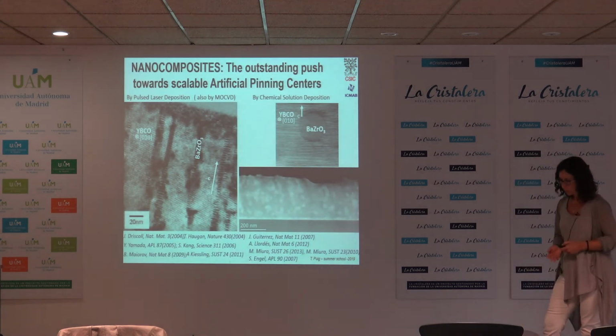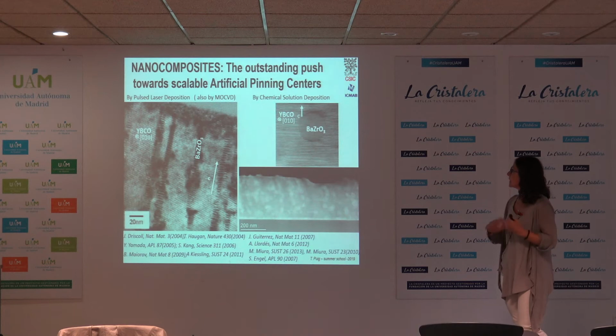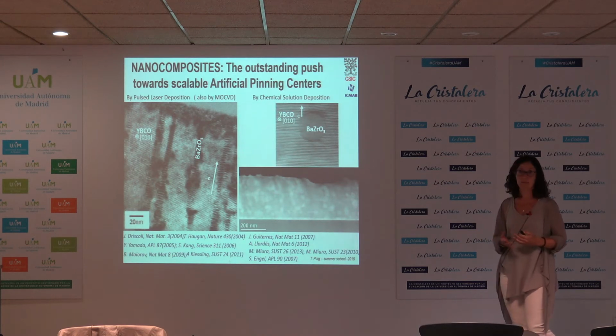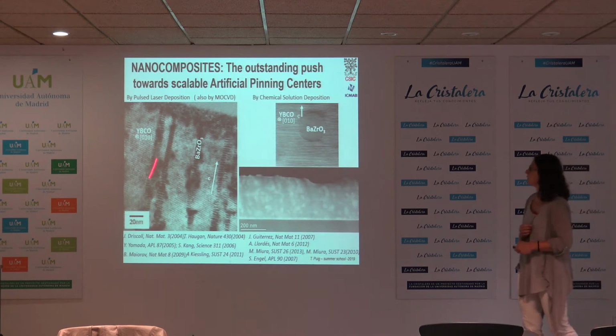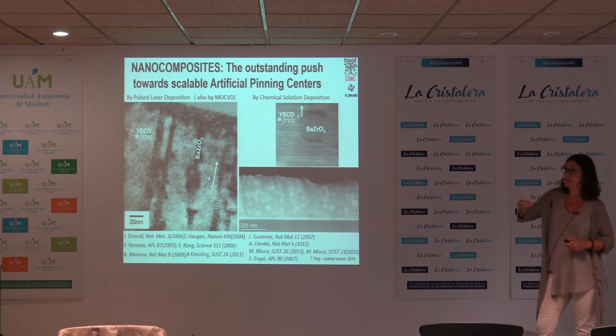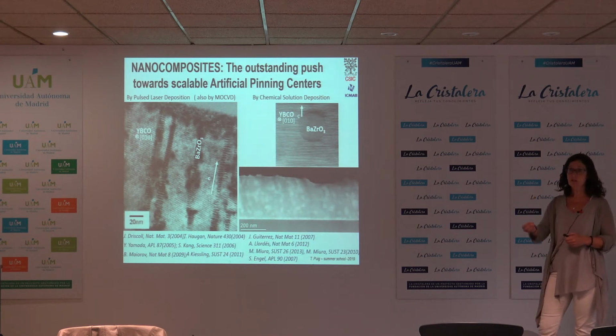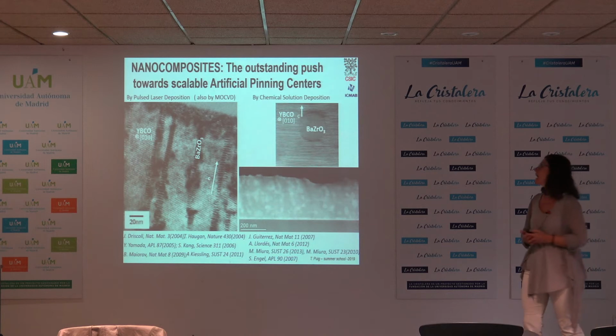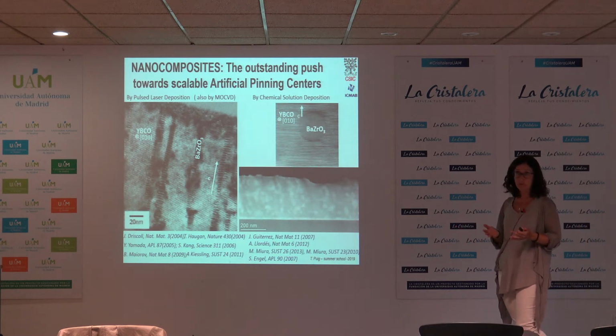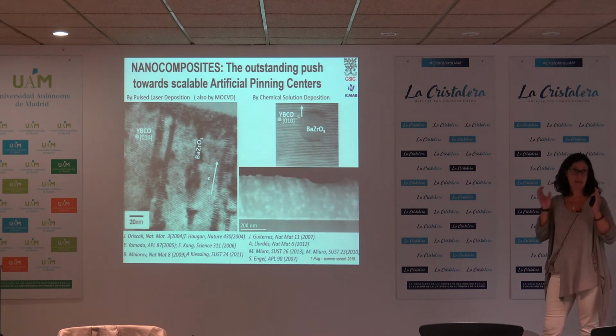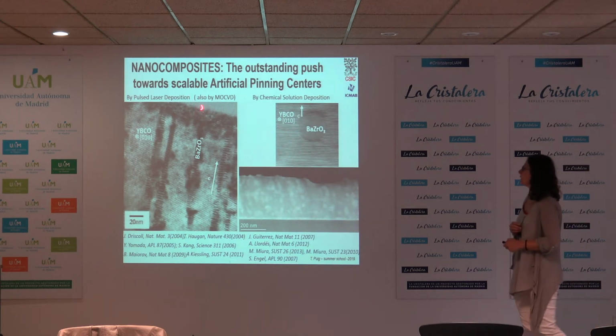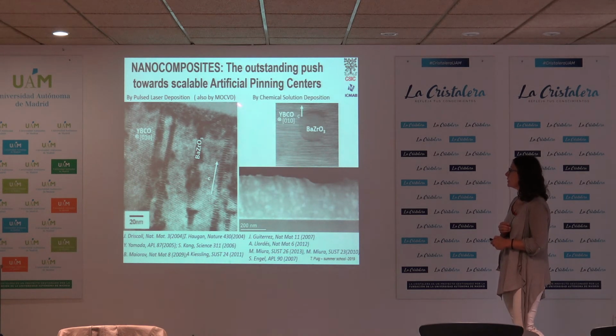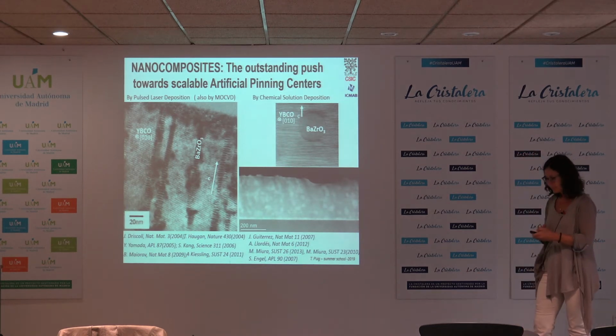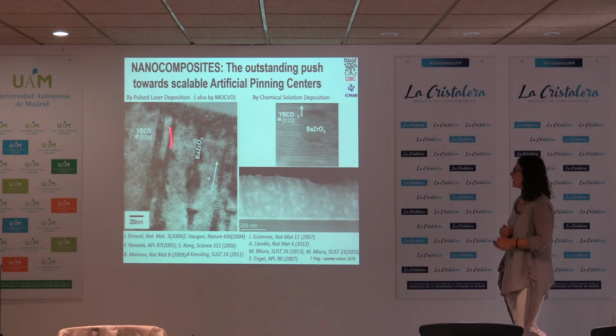So at the end, the best artificial pinning center in YBCO has been what is called a nanocomposite, and this is to be able to put a nanometric secondary phase into the material, which is not reacting with the superconducting phase, and which can be spontaneously segregated during growth, and that can have a nanometric size so that they can pin the nanometric vortices. So for techniques like pulsed laser deposition or MOCVD, it has been possible to get nanorods. These are nanoparticles which are aligned in the form of nanorods, which are able to pin vortices very easily if you apply a field in the direction of these rods.